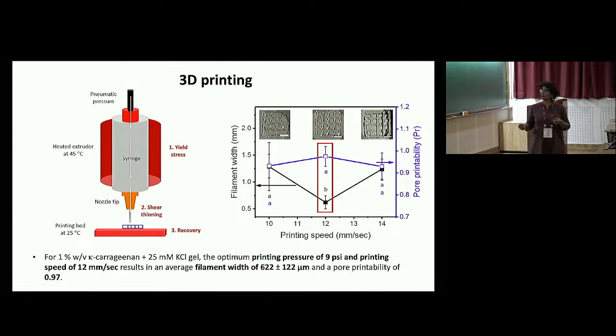So we did some trials to figure out what temperatures I should have when these materials start to come out of the printer and I'm able to print. So basically at room temperature we could print, but the results were not very reproducible. So we did experimentation and saw that if we heated it a little bit to like 45 degrees Celsius and then did subsequent printing at 25 degrees Celsius, we could print good structures. So these are our printing conditions.